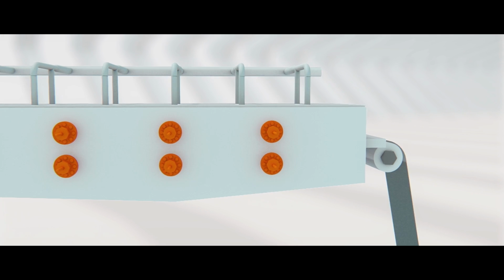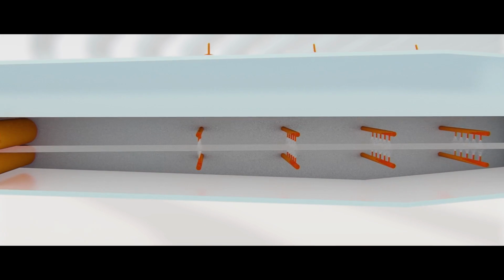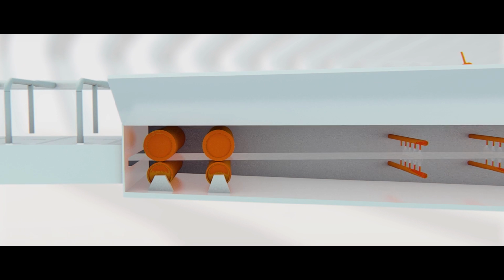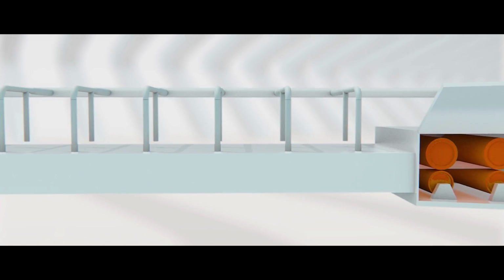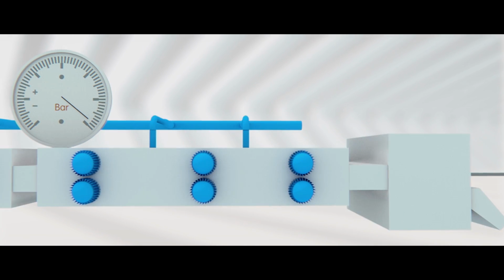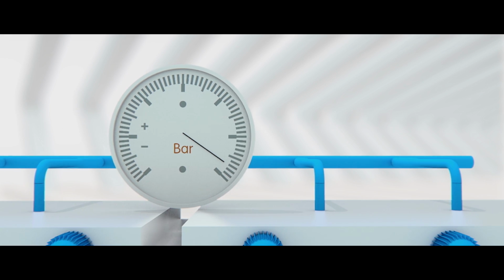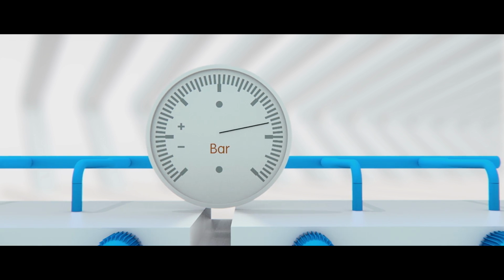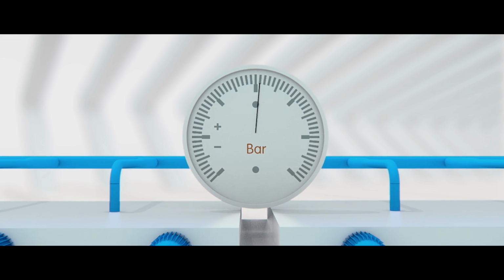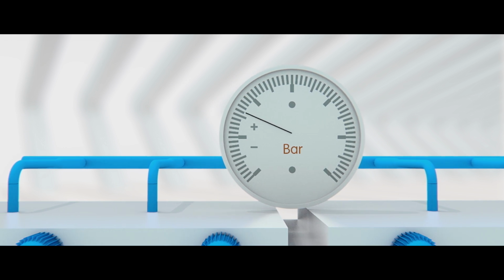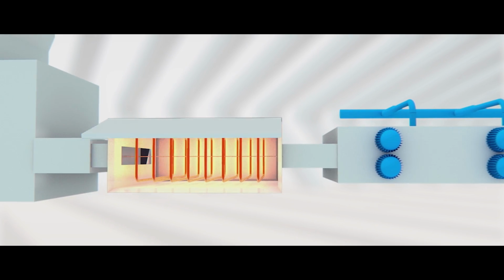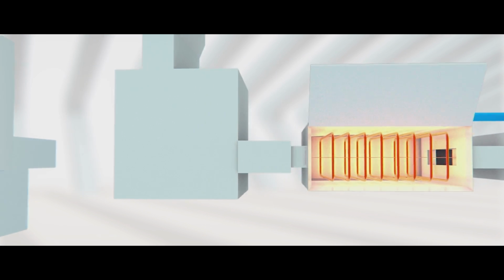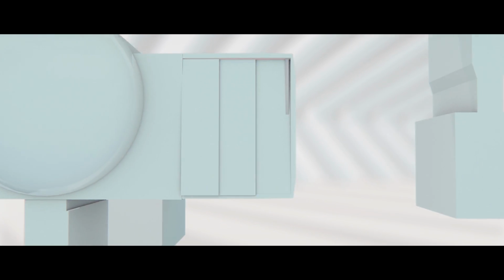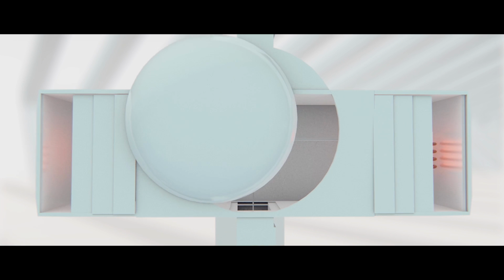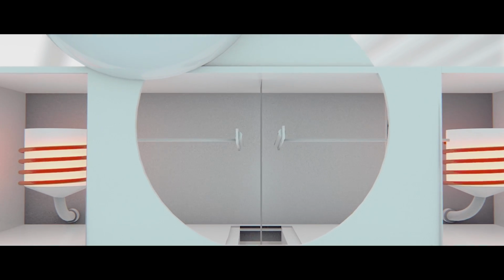The first step consists of degreasing the strip so that all organic residues are removed. The steel strip is then transported towards the heart of the JVD. The lock at the entrance of the vacuum zone enables the steel strip to pass towards a vacuum atmosphere. After being reheated slightly, the strip is transported towards the zinc coating area of the JVD, where the zinc is vaporized onto the strip by a movable blower.